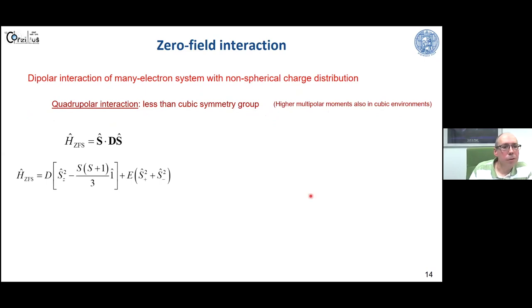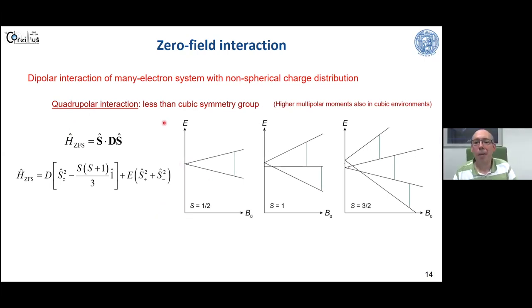So here you can see the Hamiltonian of the zero field splitting, and in its own eigenframe, this is then the contribution of the different projection operators. So the zero field interaction lifts the degeneracy of the spin system at zero magnetic field. And this then causes a splitting at higher magnetic fields into several transitions. If you have a doublet system, then you have one transition. A triplet, you have two transitions. In a quartet, you have three transitions, and so on. And these are symmetrically split, at least in the high field limit, around the isotropic g factor in this case.